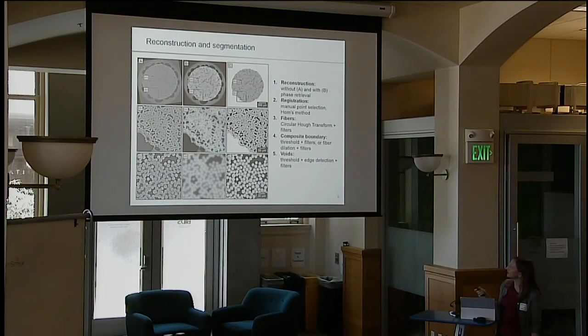So the first step of the segmentation is to identify the fibers. For this, we use the images without phase retrieval, which are shown here, because the edges of the fibers are a lot easier to detect. So we use the circular Hough transform and then several other filters, including 3D information as well, to filter down and improve the segmentation. The next step would be to identify the boundary, which is done with a threshold primarily, and then several other filters to improve that as well.